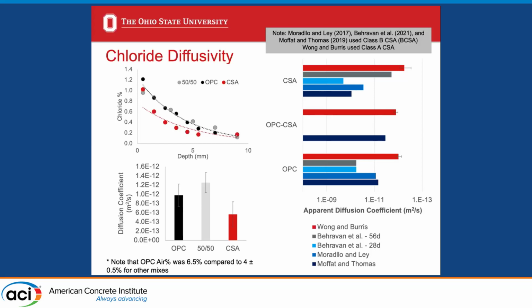And so finally, we did an assessment on durability, focusing in on chloride diffusivity. And so we looked at only a couple mixes. This work is quite a bit more involved. And so we assessed OPC, 100% OPC mix, the 100% CSA mix, and a mix that's 50-50 of each of those materials. And overall, what we can see is that the OPC and the blended mix performed very similarly, and the CSA had slightly better performance at 28 days. And the diffusion coefficients as well are shown below. We see pretty similar performance from the OPC and the blended mix, and slightly better performance from the 100% CSA mixture.